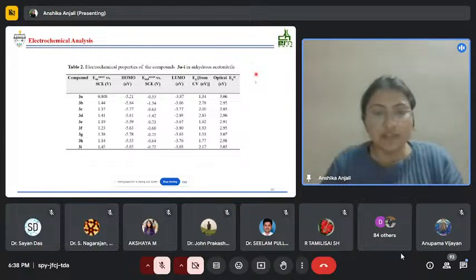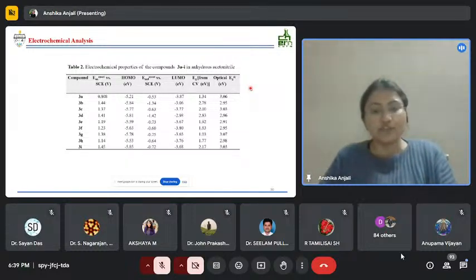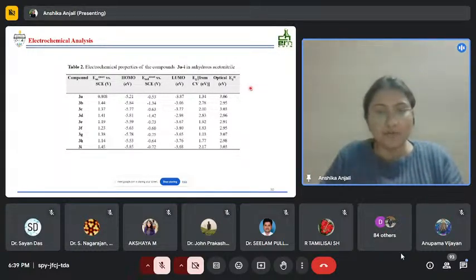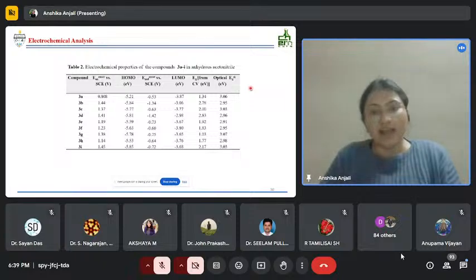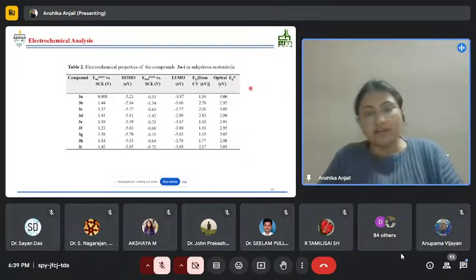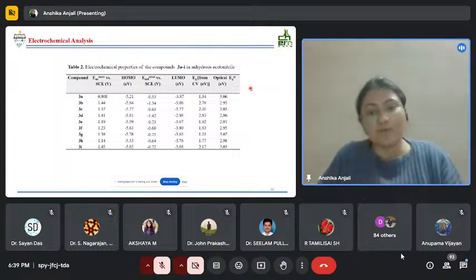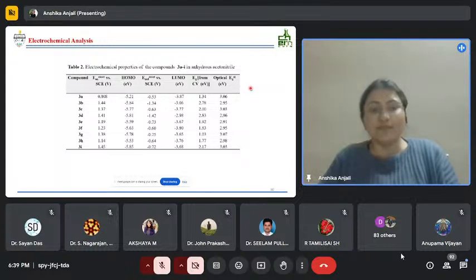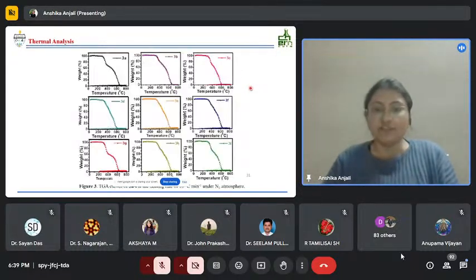So for these compounds, their HOMO energy level lies in the range of minus 5.21 to minus 5.85, and LUMO energy levels lie in the range of minus 2.98 to minus 3.87. So these compounds can be used as ambipolar molecules because their HOMO and LUMO levels are in that range.